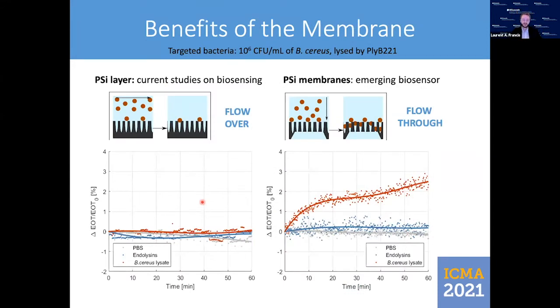What is the performance of the porous silicon sensor? For most porous silicon-based sensors found in literature, there is a flow-over operation where the analyte is simply flown over the porous layer, which is what we see here. In that case, no analyte is captured in the porous layer, and with our detection protocol, no bacterial lysate can be detected. That's what we see in the graph here. Indeed, the effective optical thickness shift measured during the bacterial lysate detection, in red in the graph, is comparable to the ones measured during both negative control in buffer and with only endolysin in order to make the check.